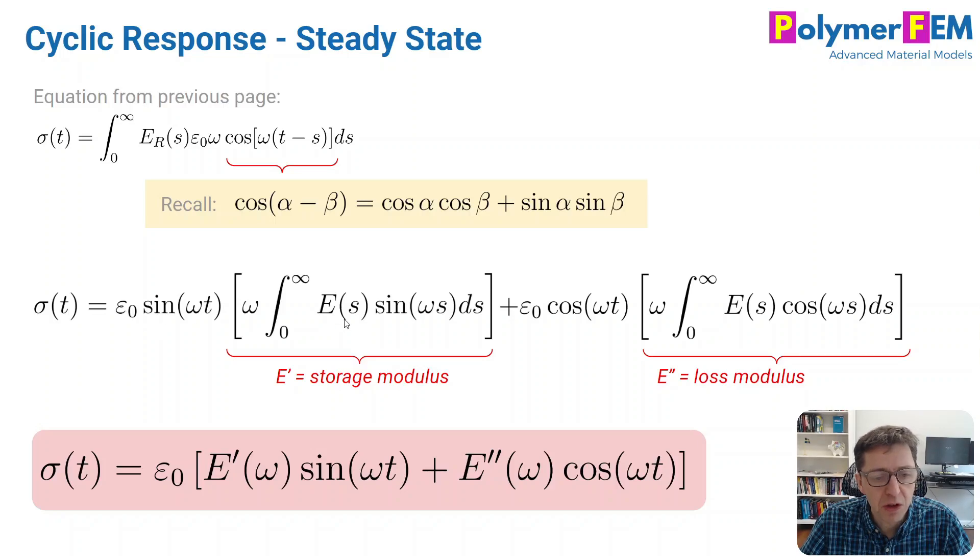That the stress is proportional to a value of sine times a storage modulus plus a cosine term and a loss modulus. And this is the definition of the loss modulus, this is the definition of the storage modulus, which will be dependent on the frequency itself. So that's how linear viscoelasticity would respond in steady state under a cyclic load, and that's summarized at the bottom here with the storage and the loss modulus. And those are the terms that the DMA test machine will provide to you.